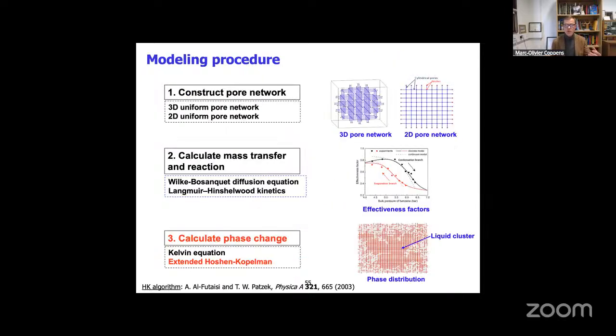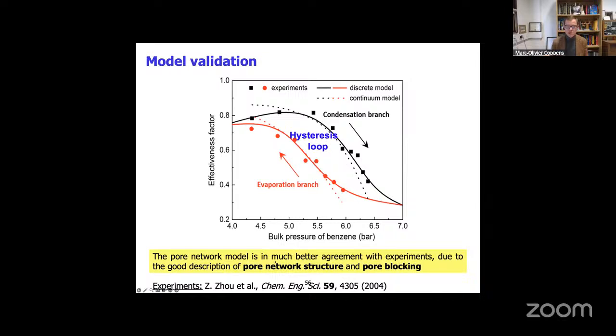We can construct pore networks, evolve their geometry, calculate mass transfer and reaction, and calculate even phase changes. And just to show you one example where we were able to compare with experimental results, we show that if you use a continuum model, you don't get as good agreement with the experimental results as using a discrete model for the effectiveness factor for this reaction of benzene hydrogenation, as a function, in this case, of the bulk pressure of benzene. This matters because if you increase the pressure, you will have increased condensation in these pores, so you have capillary condensation effects. And so you get a hysteresis effect when you increase and then decrease the pressure. You are moving through this hysteresis loop. And so we were able to get excellent agreement between experiments and theory.